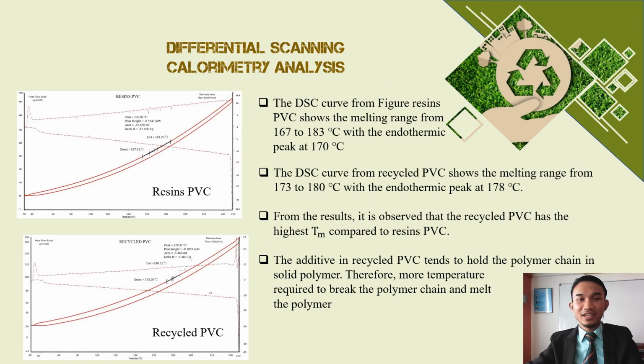Next, I will share the result from the DSC analysis. The DSC curve from resin PVC shows the melting range from 167 to 183 Celsius with the endothermic peak at 170 Celsius. The DSC curve from recycled PVC shows the melting range from 173 to 180 Celsius with the endothermic peak at 178 Celsius. From the result, it is observed that the recycled PVC has a higher melting point compared to resin PVC. The additive in recycled PVC tends to hold the polymer chain in the solid polymer. Therefore, more temperature is required to break the polymer chain and melt the polymer. The melting point obtained in this analysis was used to set the temperature in the extrusion and compression process.